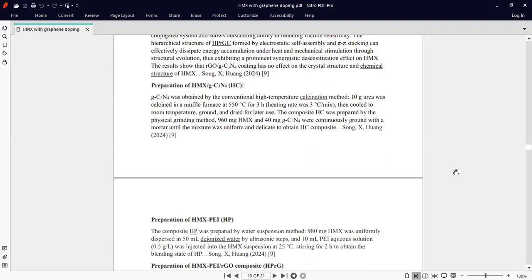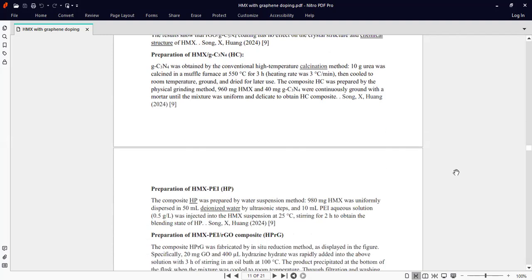Preparation of HMX g-C3N4 HC. g-C3N4 was obtained by the conventional high-temperature calcination method. 10 gram urea was calcined in a muffle furnace at 550 degrees Celsius for 3 hours. The heating rate was 3 degrees centigrade per minute, then cooled to room temperature, ground and dried for later use.